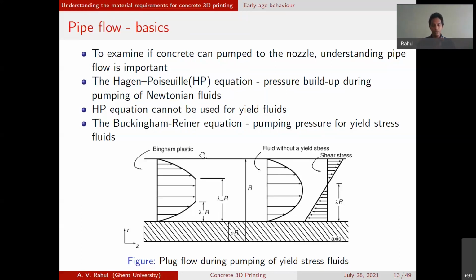Now, if you do the same analysis in the case of a Bingham plastic material or yield stress fluid, you would see that it follows a parabolic profile initially, as you see here, and then towards the center, you see a plug forming like this. So you see a parabolic profile, and then you see a plug forming at the center. This again becomes very clear if you look at the shear stress diagram. It looks quite similar to this. The shear stress is maximum towards the edges, and then it starts to decrease as you proceed towards the center of the pipe.